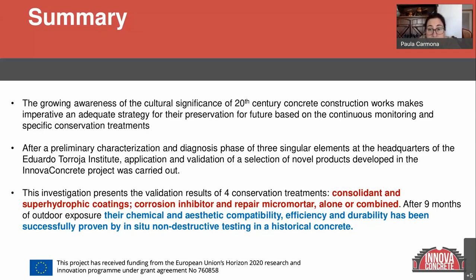And this investigation presents the validation results of four conservation treatments: a consolidant, a superhydrophobic coating, a corrosion inhibitor, and a repair micromortar, applied alone or combined after 9 months of outdoor exposure. Their chemical stability, aesthetic compatibility, efficiency, and durability have been successfully proven by in situ non-destructive testing. And finally, next, please.